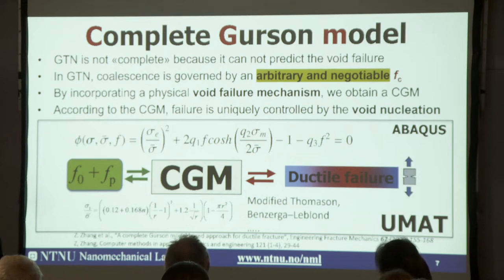Many years ago, when I was doing my PhD, I realized the Gurson model was not complete in the sense that it cannot predict void failure. In the GTN model, coalescence is governed by an arbitrary and negotiable critical void volume fraction, FC. That I don't think is good. So I realized that by incorporating a physical void failure mechanism, for example, the modified Thomason's criteria, or Benzerga and Leblond's criteria, there are many such physical failure mechanisms available. By incorporating a physical void failure mechanism, we obtain the CGM, the complete Gurson model.